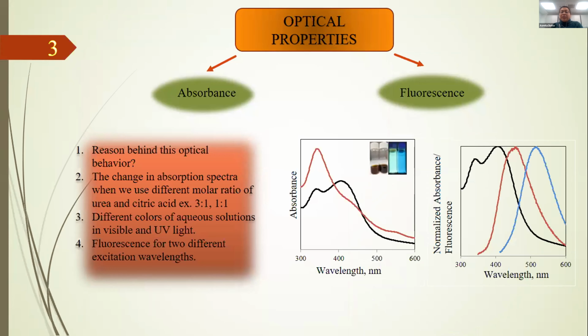The optical properties of carbon nanodots are mainly differentiated into two parts, absorbance and fluorescence. We prepare two different types of carbon nanodots by varying the molar ratio of urea and citric acid. For one of them, it's 3:1 and for the other it's 1:1. As you can see clearly, there is a difference in the color of the aqueous solutions of these two types of CNDs in UV and visible light.